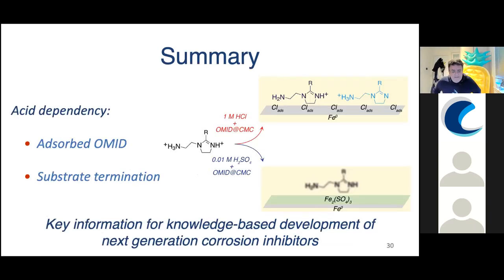So just to summarize this part of the talk, I've shown that the adsorption of the OMID is acid dependent, so it's two singly protonated states in the hydrochloric acid, and we're unsure what's going on in sulfuric acid, but also the substrate depends on the acid as well. We've shown quite different substrate termination, so these interfaces are quite different. And we believe this provides key information for knowledge-based development of next generation corrosion inhibitors.